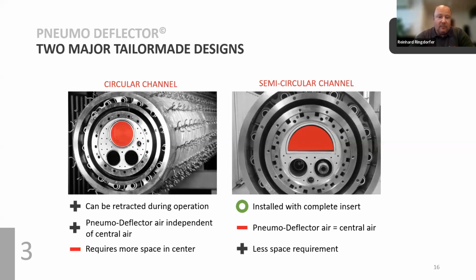The advantages are very clear here. Due to this pipe-in-pipe system, we are able to take out the secondary fuel channel during operation if there should be any kind of damage to the channel. The deflector air can be adjusted independent of the central air, but as I said before, it requires more space in the center. The other solution is the semicircular channel, which is a half-round channel, more or less. Of course, on the back side, you will have a normal flange connection.